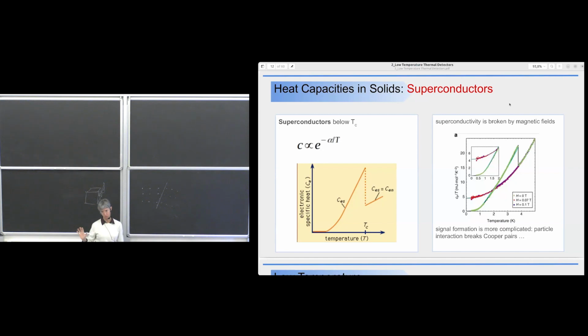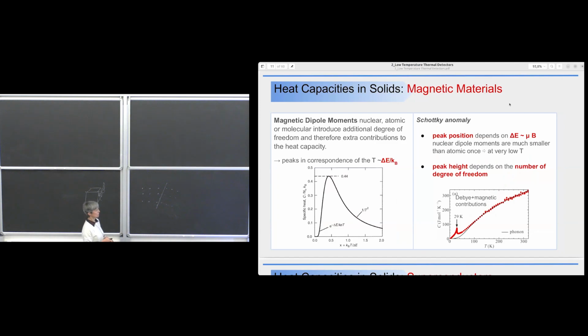large mass thermal detectors. I will try to tell you when there is a difference, but for example, when you work with microcalorimeters, some of these solutions that I tell you we have to avoid could be adopted, because the constraints are not so important. For example, if I want a high energy resolution and 1 kilogram of mass, you understand that the heat capacity has to be very, very low. While if I have 100 micrograms of mass, maybe I can accept, for example, a metal. That happened, for example, with microcalorimeters used for the neutrino mass measurement.